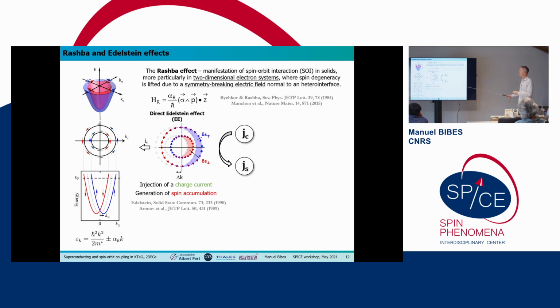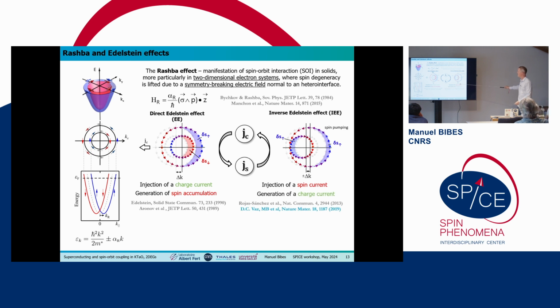And this is called the direct Edelstein effect, from Edelstein in that paper. And you have the reciprocal effect, just like you have the inverse spin Hall effect, you have the inverse Edelstein effect, which happens when you inject spins. And then if you do that, you shift the contours in opposite directions, which creates a finite charge current. So this is a charge to spin to charge conversion, okay?